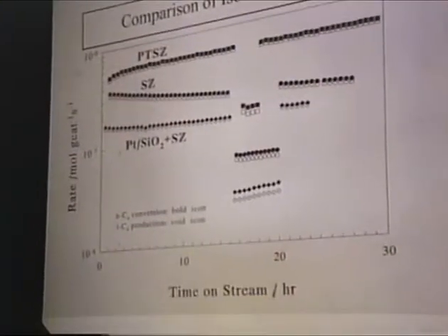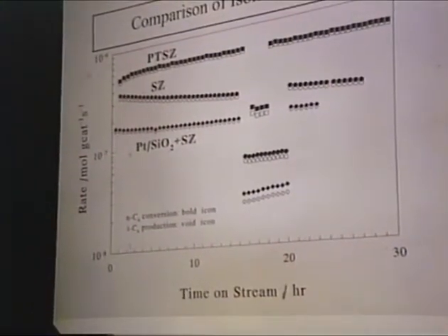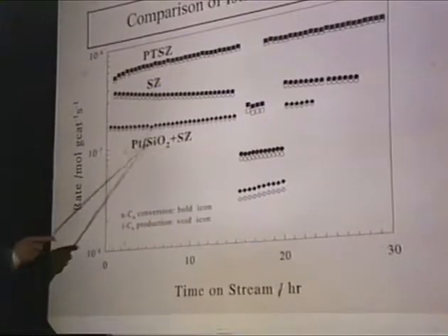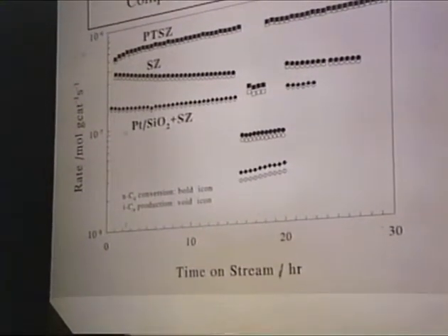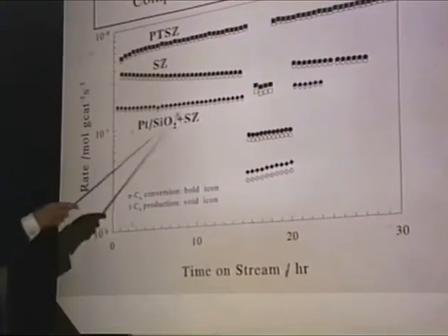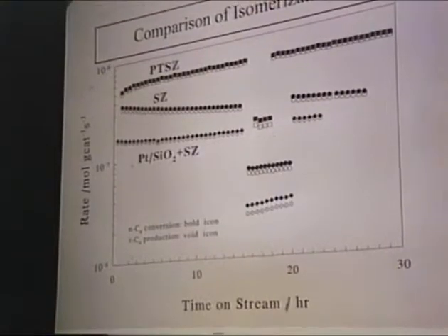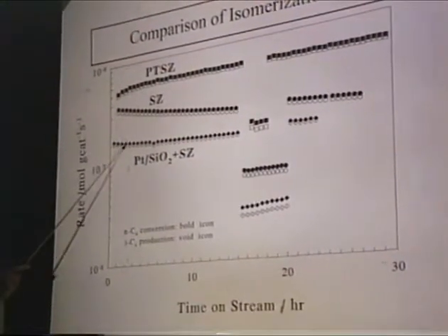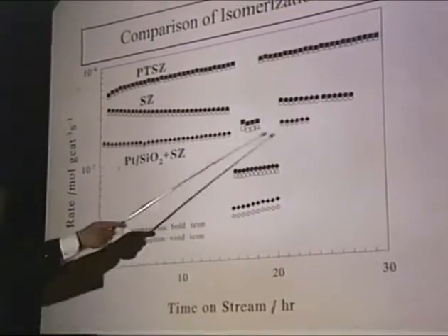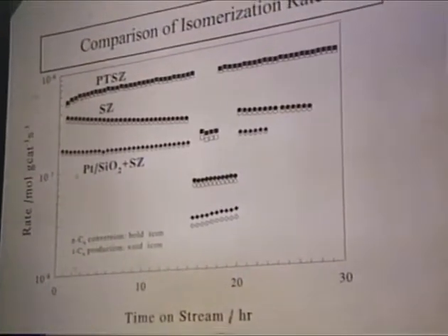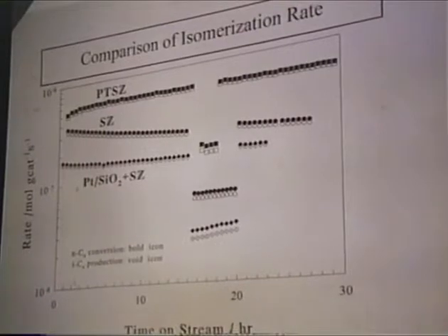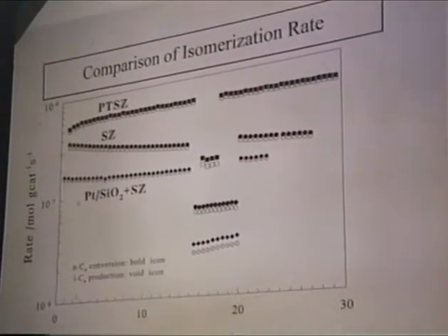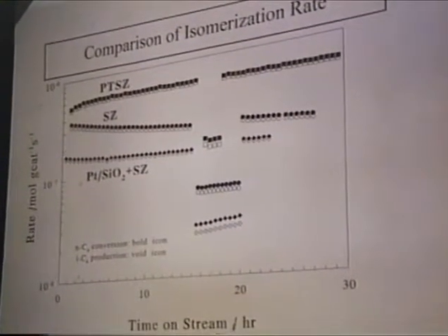And he suggested we do a double layer experiment in which we put the platinum as the dehydrogenation site before our catalyst. Then we did the experiment. To our surprise, we found that it has a reverse effect. We actually have a lower rate here. We could not understand why until we realized that in our feed we do have butene as an impurity.